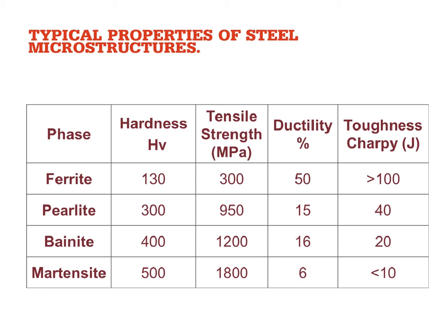So what, you might say? Yes, it's very interesting for the scientists to look at these diagrams and these fancy crystal structures. Well, the so what is, for a given piece of steel, if you heat it quickly or slowly, the hardness can change from 130 in this case to 500. The strength can vary from 300 to 1800. The ductility gets lower and the toughness gets very much lower.